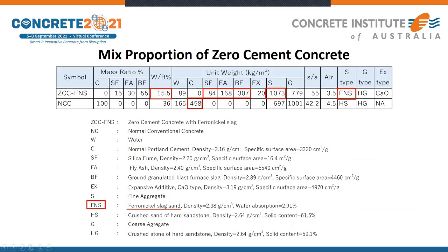This is a mixed proportion of the conventional concrete and the zero cement concrete. Look at this. The water binder ratio is very, very small, around 15%. Water is less than 100 kilos, and then we use silica fume, fly ash, and then blast furnace slag. And this is a sand. Sand is very special. FNS means ferronickel slag sand. This is very basic. This has a very good characteristic to reduce the shrinkage. And in normal concrete, we used around 460 kilos of cement.